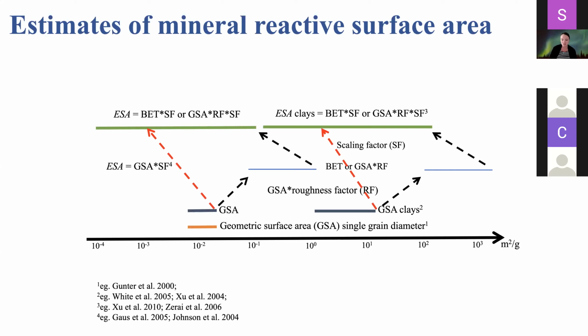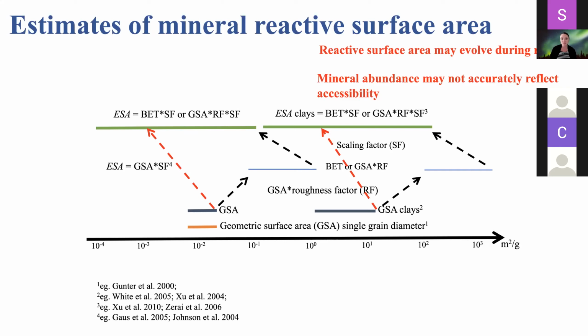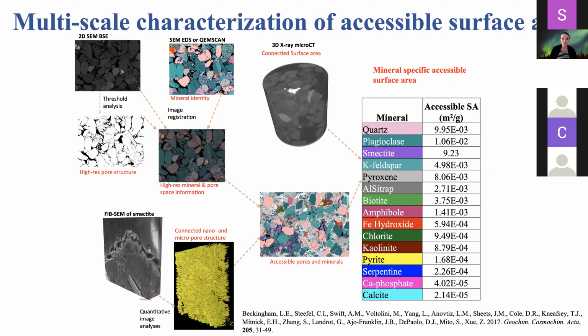The problem with this estimate is still that mineral abundance might not accurately reflect accessibility in porous media, as well as this does not account for the fact that surface areas might actually be changing as reactions progress. In some of our recent work, we have used a multi-scale, image-based characterization approach to actually quantify the accessible surface area. So we combine 2D SEM imaging with 3D FIB-SEM imaging of the clay minerals, so the nanopores here, to try to understand the accessibility of mineral surfaces to the reactive fluids. We can account for connectivity in 3 dimensions with X-ray CT imaging and actually quantify mineral-specific accessible surface areas.